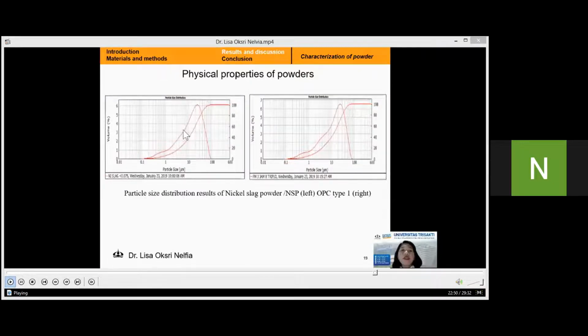The figure on the left shows the particle size distribution, with a median diameter of nickel slag powder at 15.4 micrometers, almost the same as the median diameter of the OPC type 1 at 14.90 micrometers in the figure on the right. The particle size distribution of the nickel slag powder may have some benefits in the partial replacement of cement in a concrete mixture.